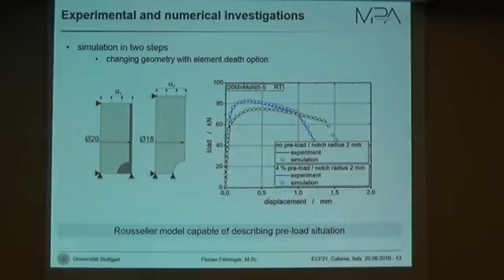So the question now is, is the GTN model capable to describe such a situation with changing triaxiality, changing geometry? Same as for the experimental procedure, we did a 2-step simulation. So we first pre-strained a smooth bar, and after 4, respectively 8% total strain, with an element death option, we changed the geometry to a notch geometry and continued with the simulation. And on the right diagram you can see, as one example, the 2 mm notch radius, 4% pre-strained specimen in blue, and you can see the load displacement behavior and the crack initiation time could be described very well by the GTN model.